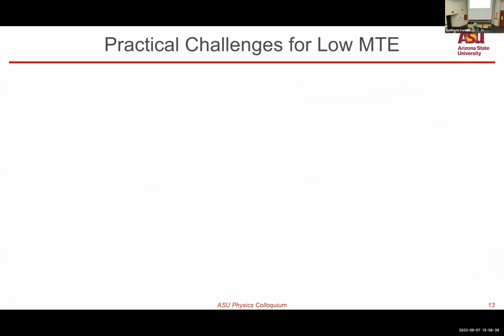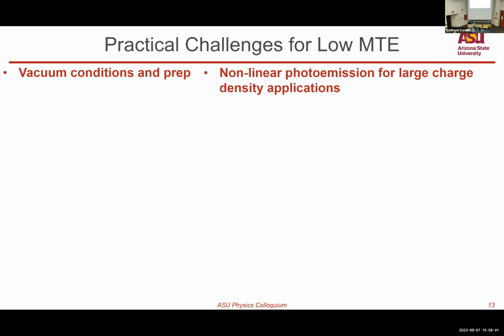Now, practical challenges. As you mentioned, first, vacuum conditions and preparations. As Will said, it wouldn't last for too long. Yes, it doesn't. And then there's also issues with nonlinear photoemissions for large charge density applications. First, we did solve this using a graphene-coated copper 110 surface. Coated with graphene, it's a really nice ordered surface. Once you put it in vacuum, it's very easy to prepare. All you have to do is anneal it to a moderate temperature.